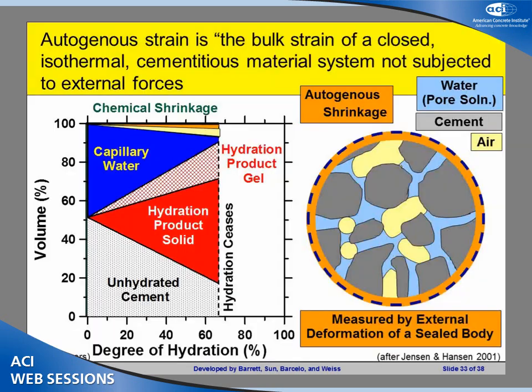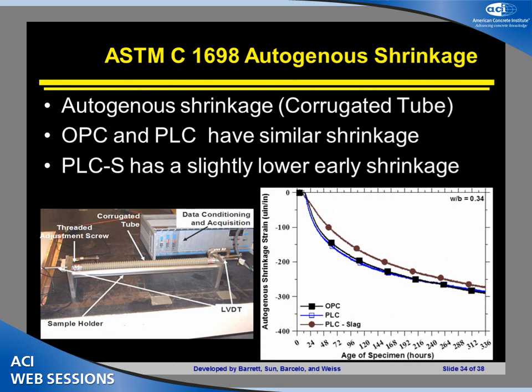The autogenous shrinkage of this system, again, autogenous shrinkage is simply the shrinkage of a closed system that's not losing moisture to the outside, not subjected to temperature change. If we look at this shrinkage from the time of setting, what we'll notice here is the black line, again, is the OPC, blue is the Portland limestone cement, brown is Portland limestone cement with slag. Out to 3 weeks, I believe is what we see on this curve, 2 to 3 weeks. We see very similar shrinkage with the slag being slightly slower, as we would expect because the slag is slightly slower to react.